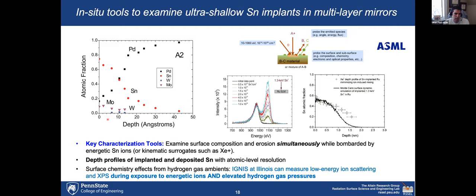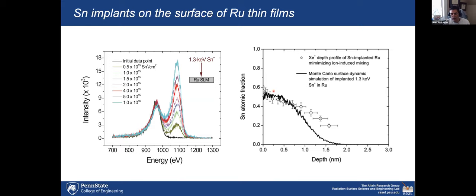So what you're seeing here is a profile in depth of angstroms. And you see here, for example, this is 1 nanometer. And we were able to probe, on a ruthenium mirror, the amount of tin that was arriving. And again, this amount of tin was driving much of the failure of these mirrors in these large lithography machines. By conducting these in-situ studies, where we actively looked at where the tin would deposit, we found that most of the tin remained in the first nanometer.